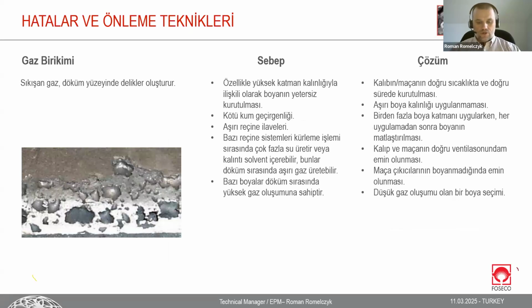Gas accumulation is very close to the previous one. Some of the solutions are similar: venting, permeability of the system. Permeability is connected with sand grain distribution, so how big or not the grains are, and what the dust content is. The very fine part of the grain size distribution is very important because it blocks permeability quite strongly, as does the addition of binders, and all the things which trap the gases in a cavity, and finally in castings. It means these gases will not have a chance to escape through the coating, the mold, or the vents especially created.